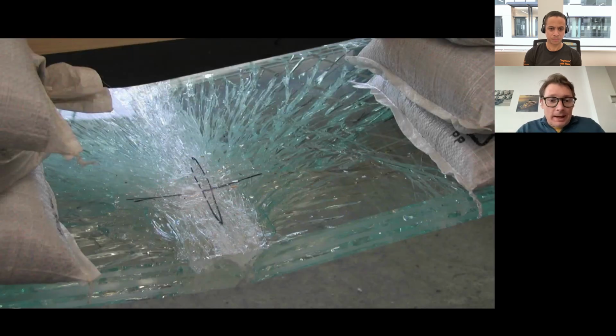And this is one of the early tests we performed with the Apple design, which was 4 sheets of glass acting as a tread. What we did was broke through all those sheets of glass and added sandbags on, so we had a long-term duration panel. And you can see that it's carrying a significant amount of load. This tread was actually 2.5 meters wide, and it's about 300 millimeters depth going to the screen. And it's carrying a significant amount of load, with all the glass failed.